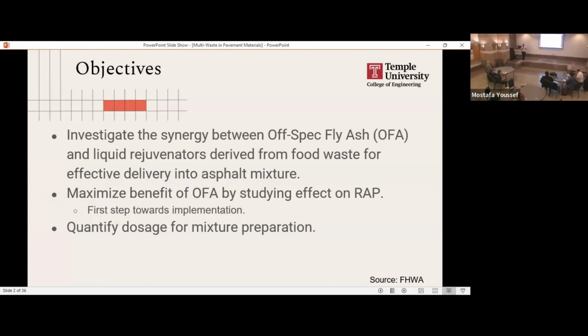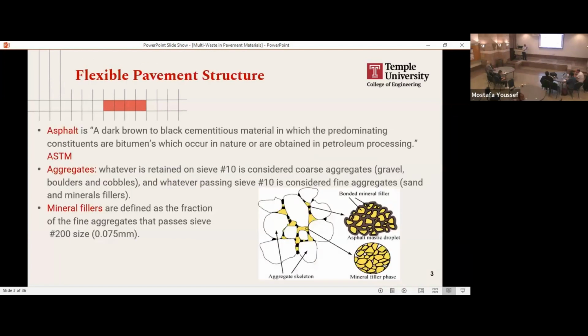You know, asphalt as it ages becomes very stiff and brittle, so it's typically prone to cracking way more when it's recycled. Combining it with an anti-aging additive, which is the fly ash, and a rejuvenator, which is the food waste oil, and increasing the capacity for incorporating recycled asphalt, we could replace a large quantity of raw material that is being mined and reduce the cost significantly. So this is the whole story, very quick. And in order for us to visualize why this is important,